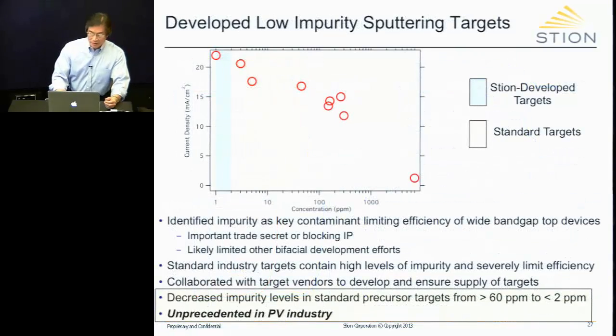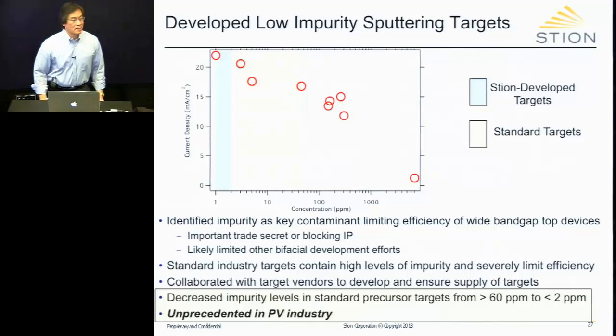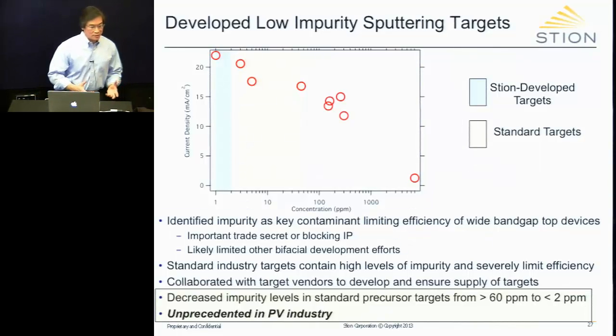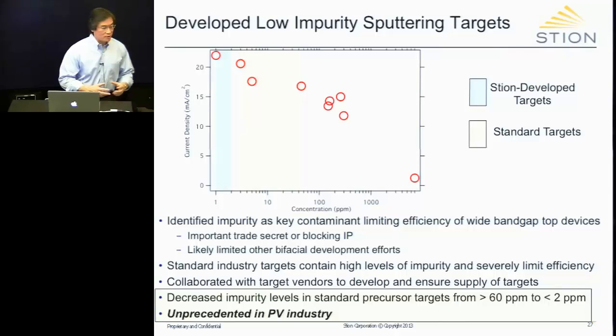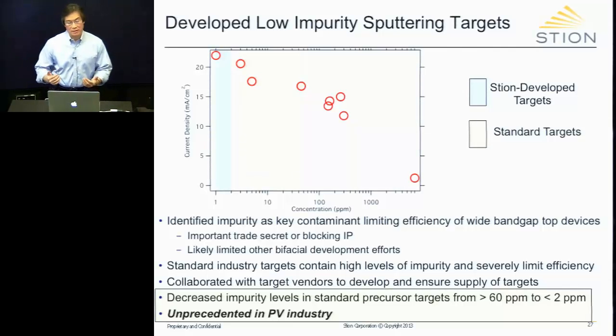It turns out that it does not take a lot to fix. When we work with them and look over their process, we suggested some very simple things that could change, and they made a big difference. So in many ways, when we do this, we actually look at target vendors as our collaborators, and it works very well for us.